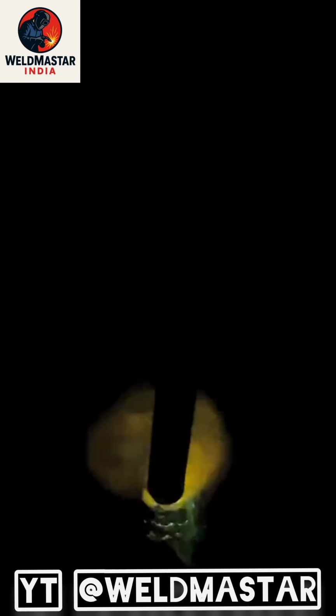Now the hole has become quite small. Also pay attention to the arc length. Do not lift the arc too high. Keep the electrode slightly pressed down. If the arc is too long, the molten pool temperature will rise rapidly, which can cause the metal to flow upward from the bottom and create defects.